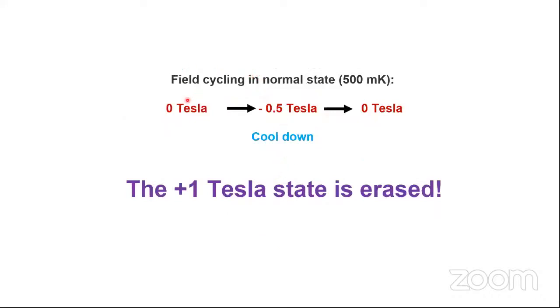Now, that means we have been able to successfully write a magnetic state at the interface. We wanted to erase it. For that, we tried different field cyclings, and we found that if we warm it up to 500 millikelvin again, that is the normal state, and do a field cycling with H max equal to minus 0.5 Tesla. That means if the state is written in the plus direction, upward direction, then I apply a magnetic field of 0.5 Tesla in the downward direction, then the plus 1 Tesla state is erased. So it did erase the magnetic information at the interface.